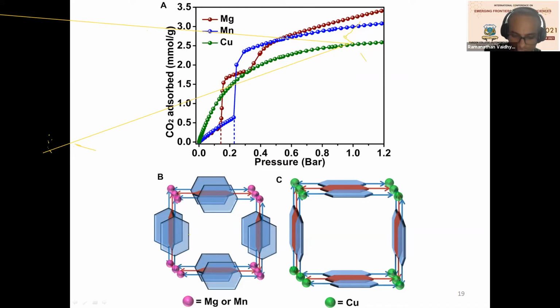Essentially, if you look at the structure of the magnesium and the manganese isonicotinate, the alternate pyridyl rings are rotated with respect to each other by 90 degrees. You need to rotate them to a 60 degree angle so that they all are equivalent. If they become equivalent, you will have more openness in the structure, and that is what happens at this particular pressure of CO2. They rotate the ring to gain the openness. Whereas in the case of copper, it is always in an open form because it is soft. Because it is always in an open form, or continuously rotates, you don't need any special force to rotate it. It is always an available form, and because of that, you don't see any gating. That is what I'm trying to show here.